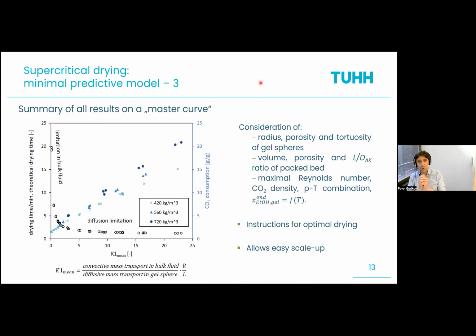If you make them small, then from the diffusion limitation case, you go to the diffusion in the bulk phase. So then the flow of the CO2 coming and facing the gel will matter, because you can increase the drying rate by increasing the flow rate of CO2. But for very big gels, of course, and that's what we can also visualize very easily, it doesn't really matter whether you do it fast or slow. The diffusion needs its time.